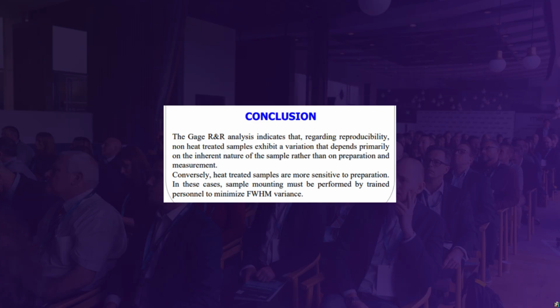The gauge R&R analysis indicates that, regarding reproducibility, non-heat-treated samples exhibit a variation that depends primarily on the inherent nature of the sample, rather than on preparation and measurement. Conversely, heat-treated samples are more sensitive to preparation. In this case, sample mounting must be performed by trained personnel to minimize full width at half maximum variance.